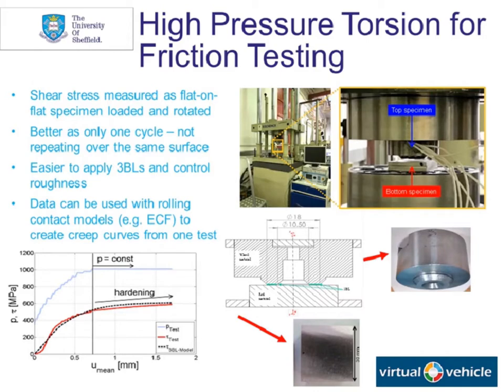So it's high pressure torsion testing. Here we're bringing two flat surface specimens together under a representative contact pressure. We're loading them together and then twisting under controlled rate of speed. This means, as you can see in the graph on the bottom left-hand side, we get a certain elastic regime, and then beyond a certain point, we get gross sliding. And we're essentially measuring the shear stress in the contact, here plotted against mean rotational distance.